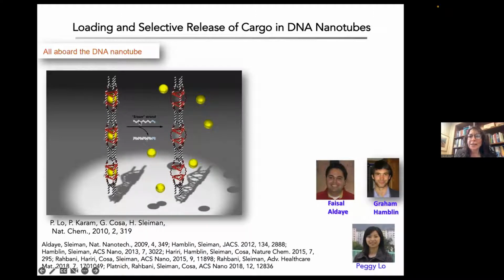So this DNA strand, here's what it's going to do. This DNA strand is going to come in and remove 2 of the strands here that make these cages double-stranded. These cages then become single-stranded as a result. Once single-stranded, the gold particle slips right out. It's not as much attracted to the scaffold, and it slips right out and it is delivered.